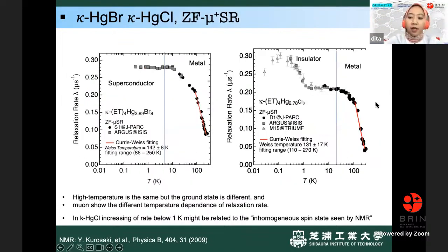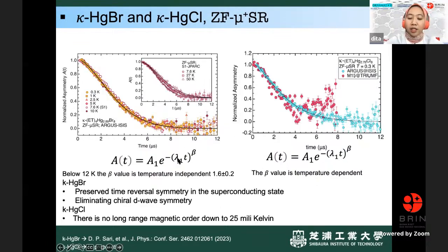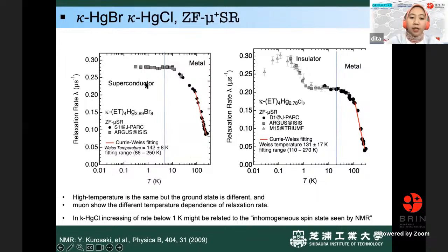Then if we plot the parameter, the relaxation rate, we see here the metal to superconductor for bromine and the metal to insulator for chlorine. At the high temperature, the situation seems to be the same, but the ground state is different, and muons show different temperature dependence. You see, this is just flat, but this is increasing, and we have a broad peak here. In the mercury chlorine, the increase of the rate below 1 Kelvin might be related to an inhomogeneous spin state.